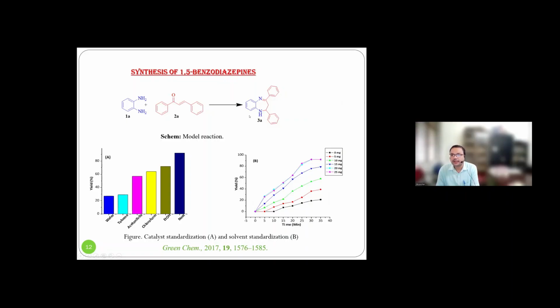After getting a good yield of the benzodiazepine, we standardized other reaction parameters, like solvent. We did the solvent screening, and the solvent-free reaction condition shows the maximum yield of the reaction. Similarly, we did the catalyst loading experiment, and you see that 25 mg of catalyst shows the maximum yield of the reaction.